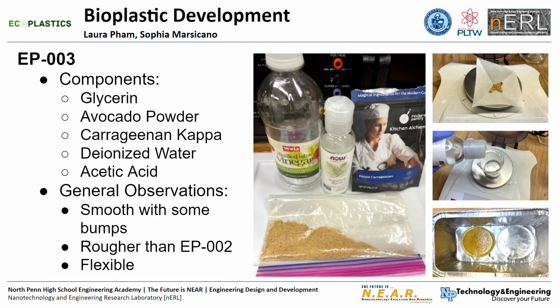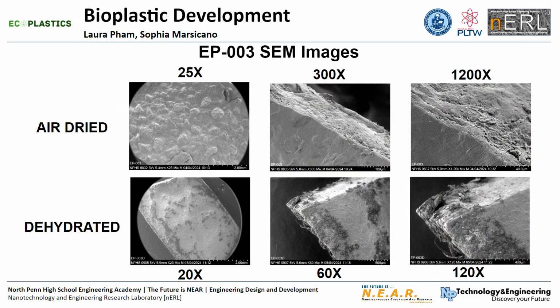EPO3 was exactly the same as EPO2, except for the addition of avocado powder. The avocado powder added noticeable texture to EPO3 as it was much rougher than EPO2, yet it was also more flexible. And as you can see in these SEM images, the avocado powder is spread throughout the sample, which is especially noticeable in the cross-section.